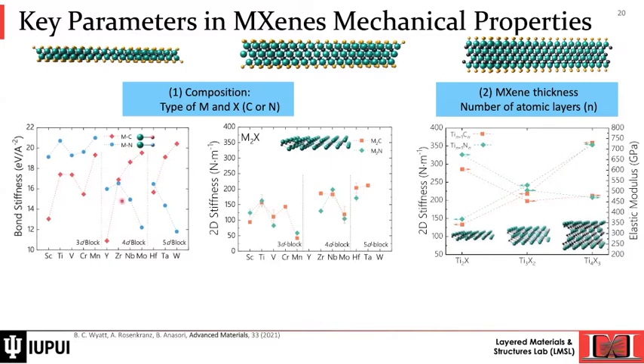So here we showed, again, these are all part of this review paper, that by changing the transition metal, M for transition metal, and carbon, we know that the bond stiffness will change. And from the bond stiffness, the 2D stiffness and the modulus will vary. So if you're looking for something stronger, obviously, you need to go, for example, to niobium, molybdenum, or tungsten in the carbide MXenes. Now, the 2D stiffness also the same way.